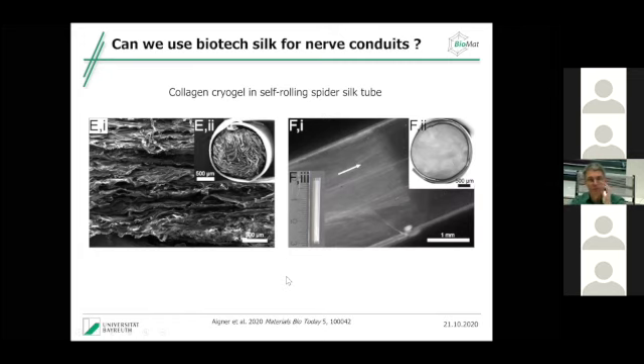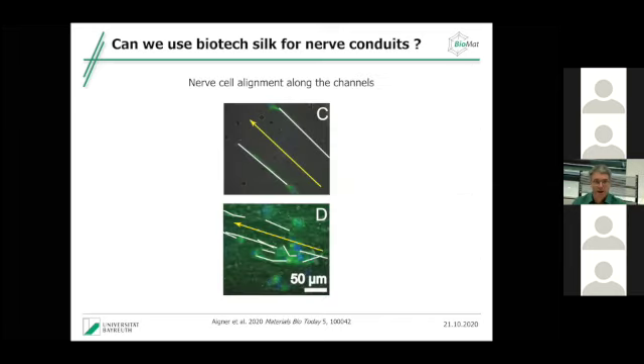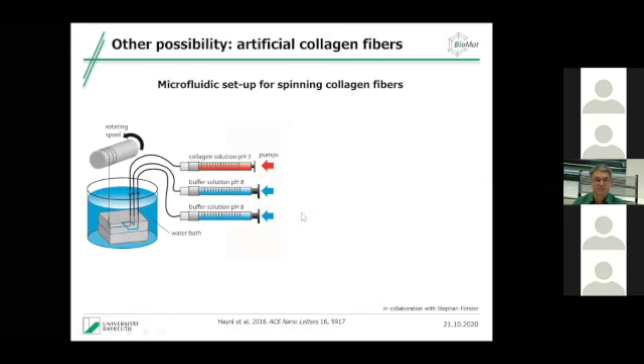Same principle as with the heart muscle regeneration. We put the nerve cells already along the structure, so we don't have to wait until they grow in and find their place. We put them where they should work. That's the idea. And then you see that the nerves nicely align along the channels in the cryogel or along the fibers, and they get functional.